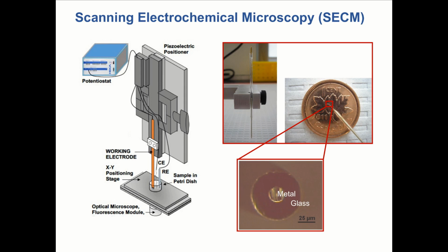Here we see the heart of this instrument is a microelectrode, shown in the right-hand side figure, which is again a metal wire, but this time on the micrometer scale, sealed in a glass capillary. When we look at the tip, we see this metal in the center and the glass surrounding this metal where we carry out the electrochemistry. This electrode is mounted onto a Z-axis positioner, shown in the left-hand side figure in orange, and this Z-axis positioner can approach the sample precisely in 1 nanometer steps. We can position this electrode very precisely at a desired height on top of a sample. Our sample sits in a Petri dish that is mounted onto an XY axis positioning stage, so that moves in X and Y. So we have all 3 dimensions to position our electrode in close proximity to a biological sample.